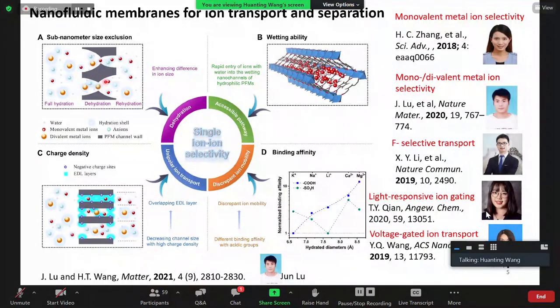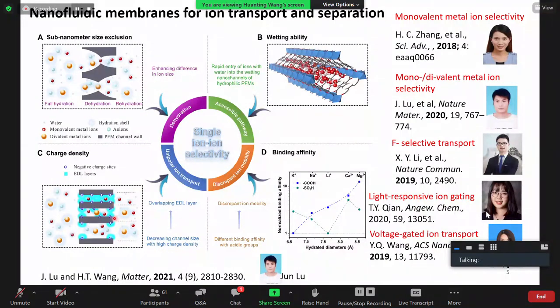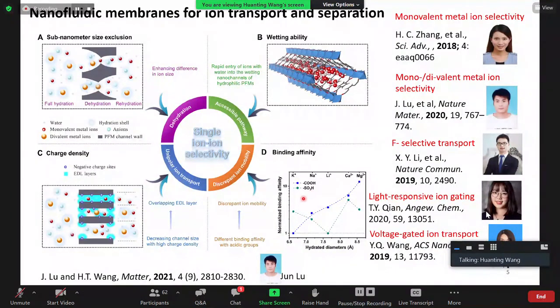Another factor is wettability — you need ions to be able to enter the material. Charge density and charge distribution are also very important, especially with very small pores, where the electric double layer of the ions can overlap with the pore size. Surface charge and surface functional groups are therefore very important.